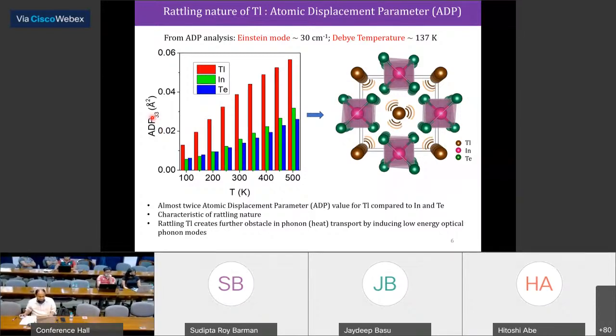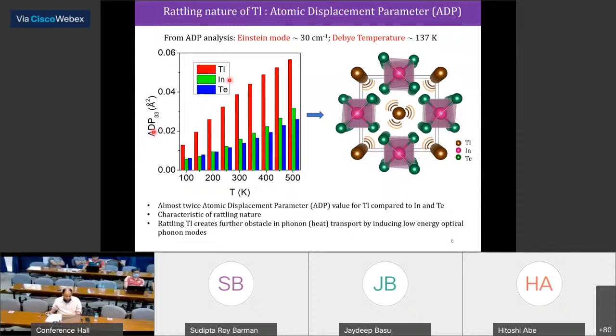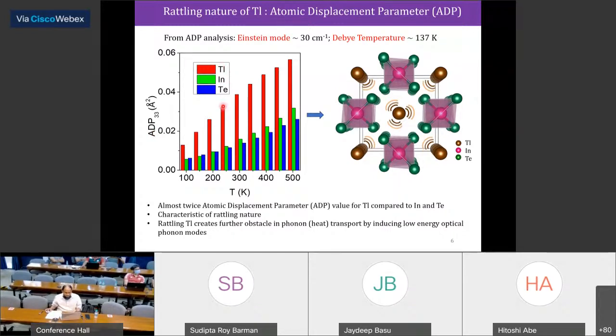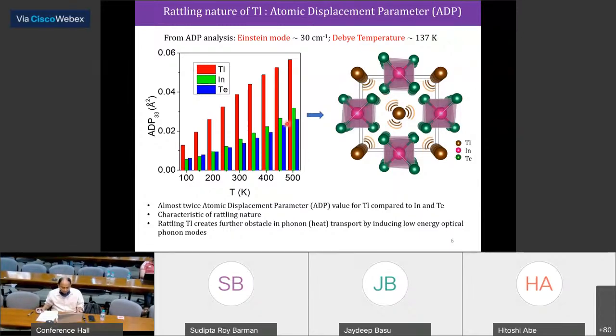So the next parameter we have analyzed from this temperature dependent PDF is the atomic displacement parameter, which is nothing but the thermal parameter. You can see this thermal parameter of thallium is much higher compared to the other two atoms, almost double, and that means this thallium rattles in this channel. So this is a classic intrinsic rattling we have seen in this compound. From this rattling ADP, we have estimated the Einstein mode. Einstein mode is nothing but the low energy phonon mode, which is about 30 inverse centimeters.